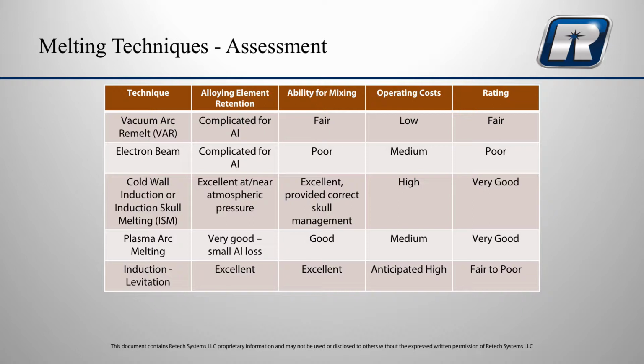The same goes for plasma arc melting. You can actually melt at atmospheric pressure and lower the aluminum loss. Same assessment, excellent for induction levitation. With regard to mixing, as Mr. Alexandrov mentioned, sometimes in VAR melting you actually have to melt quite a few times in order to get it to mix. So we rated that as fair.